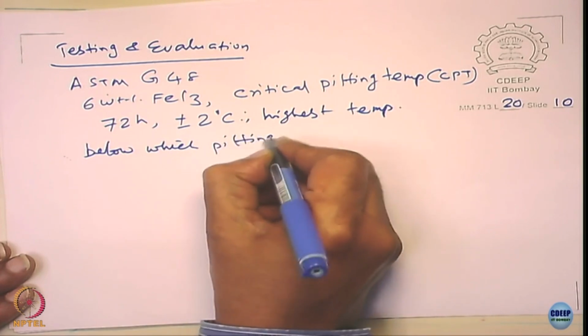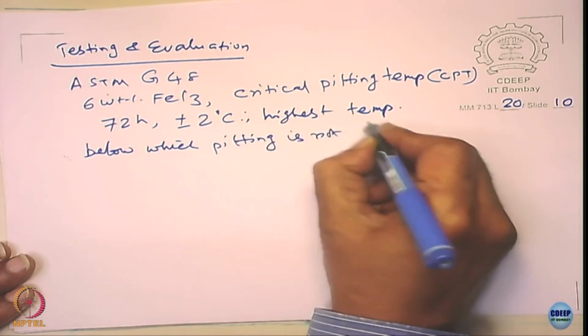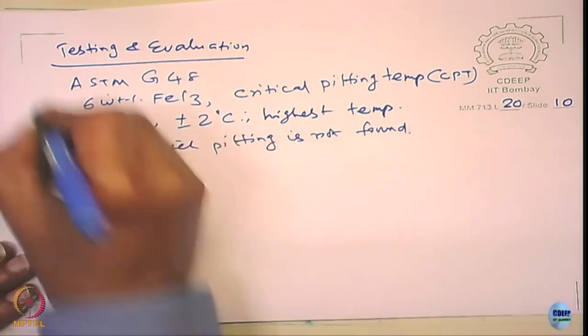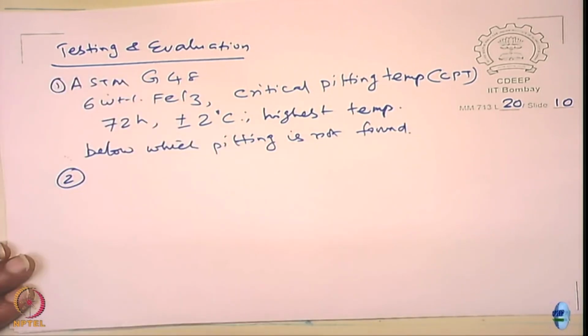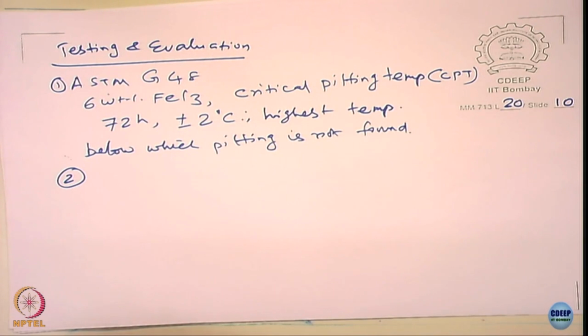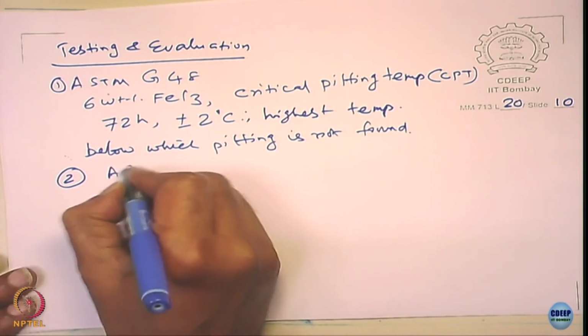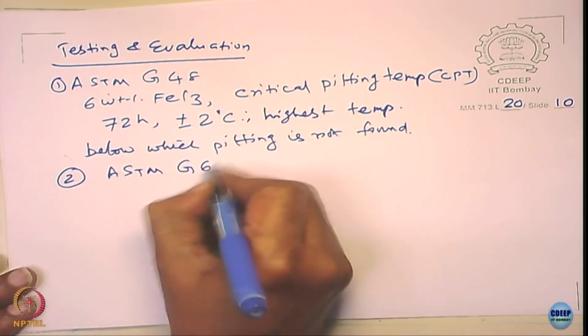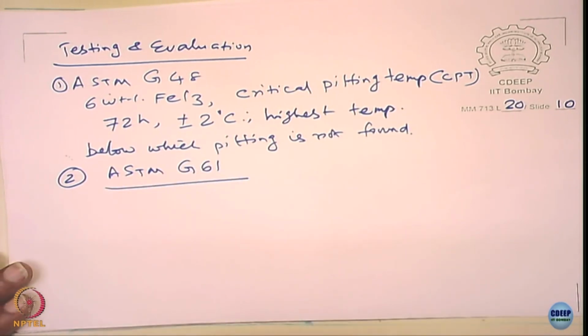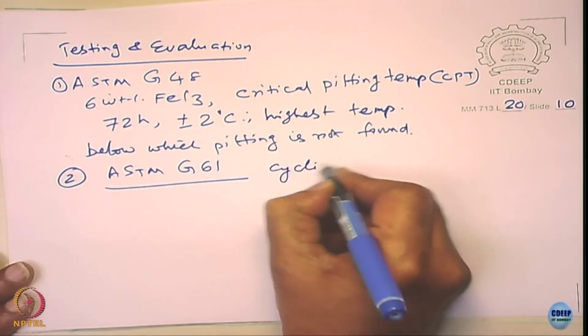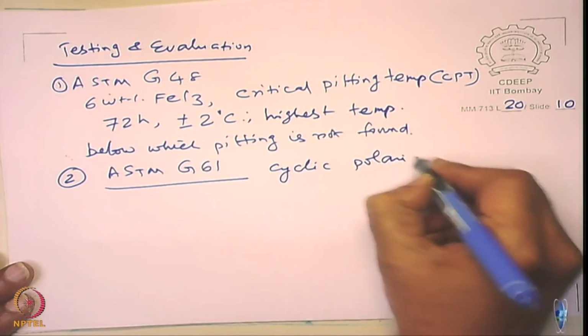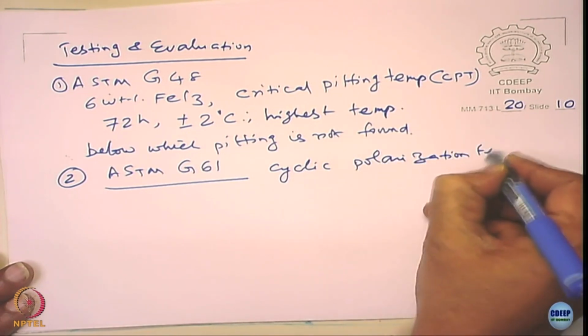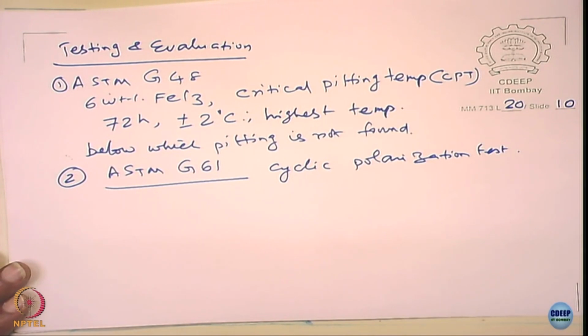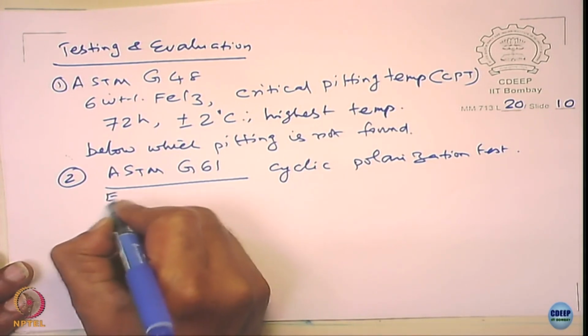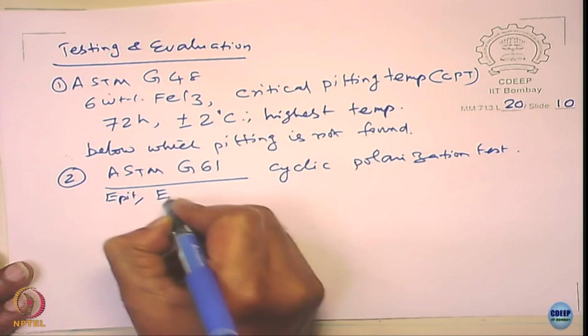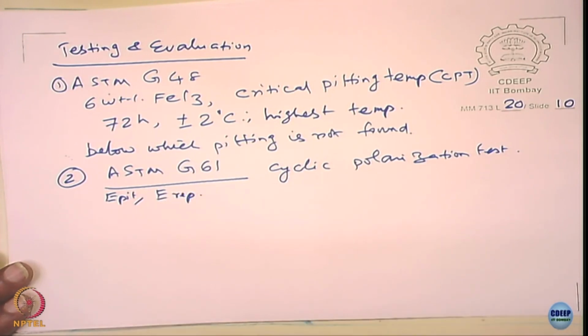Pitting is not found. Second one is also we have ASTM G61. It is cyclic polarization. Okay. What you do here, you determine E pit, you determine the E repassivation potentials essentially, right.